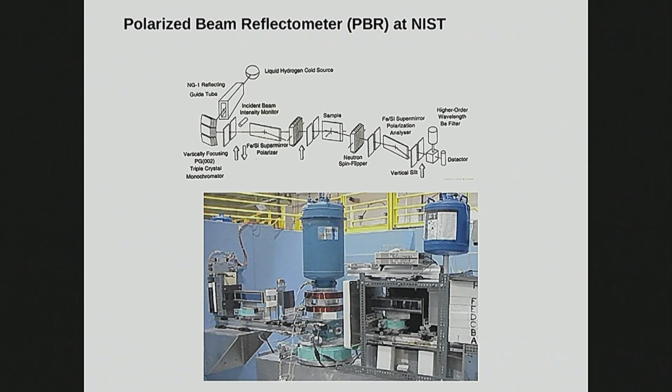There's how you make a reflectometer, okay? You monochromate the beam to get one narrow wavelength bandwidth, basically monochromatic with delta lambda over lambda of the order of 1%. And then have it reflect from a sample with a very well-defined angular divergence that is created by this pair of slits a distance apart.